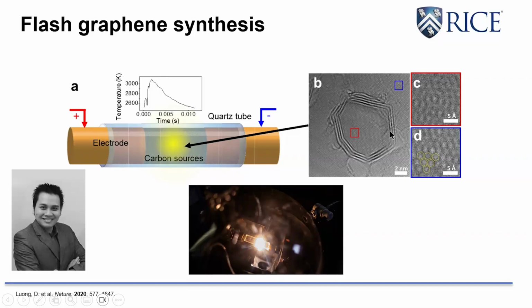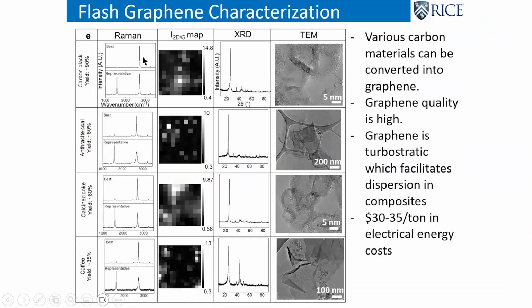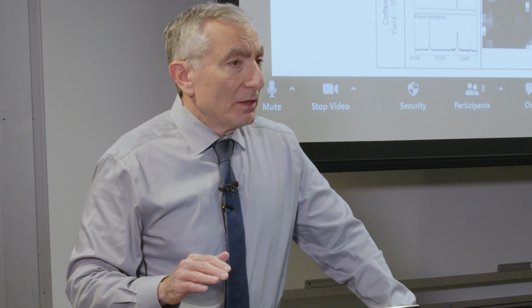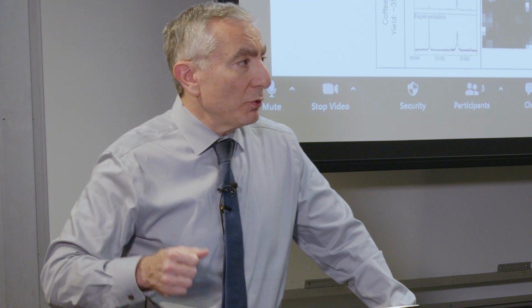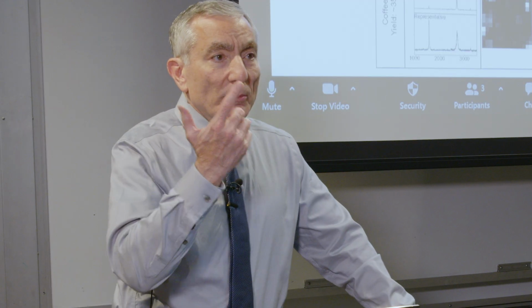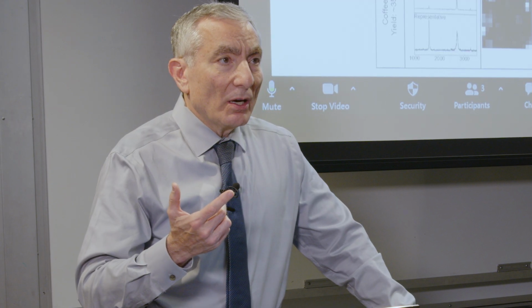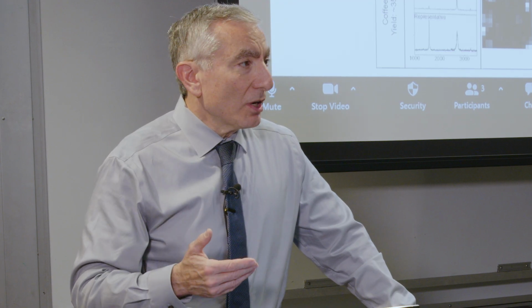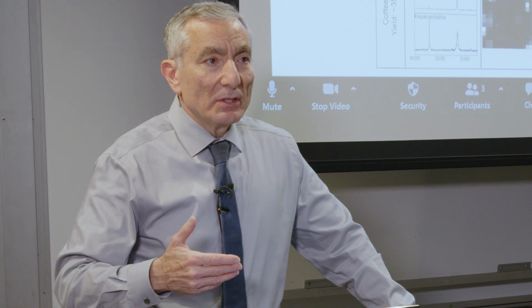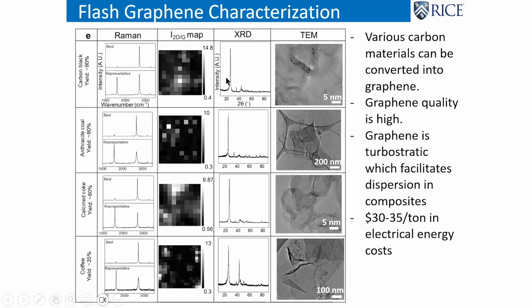And this is what the graphene looks like. And you can see this pattern here. So he did a bunch of Raman spectra, which will tell you the quality of the graphene, and you can see some of the best graphene that's ever been made has been made now by this procedure because it got so hot. Remember, when we were growing graphene on copper, that copper was getting to about 1,000 degrees. This is 3,000 degrees, so it's really hot. It's so hot that if you have aluminum in there, if you have silicon in there, they're subliming out, they're distilling out. They'll come out at about 2,600 Kelvin, and this is over 3,000 Kelvin. So they come out, and so you get a very pure form of graphene.